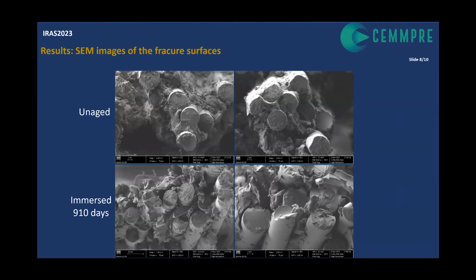In this slide, we have the fracture surfaces analyzed using a scanning electron microscope. The two images above refer to the control sample, while the ones below refer to samples immersed for 910 days. It is noticeable that the fracture surfaces of conditioned specimens exhibit a significant fiber-matrix separation when compared to the unaged samples. The unaged samples present a much better bonding between the fibers and the matrix, and accordingly, it can be said that the reduction of the fatigue performance was caused by this phenomenon, and by improving the bonding between the fibers and the matrix, we could enhance the fatigue performance of glass fiber reinforced polymers in marine environments.